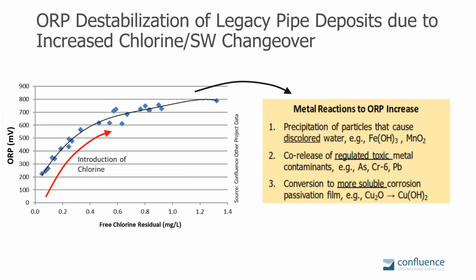An example of the other direction, of increasing chlorine. We're going from unchlorinated wells to chlorinated wells, or areas that historically have consistently had low chlorine, and all of a sudden you make a change, add booster disinfection to try to solve that, and you rapidly increase the chlorine. The types of problems we see, as I've mentioned, are precipitation of particles, such as iron and manganese, that causes co-release of those regulated metals, change in the biofilm, and a quirk with copper, which behaves differently than lead. When you're in low chlorine it forms less soluble copper species, and as you add chlorine, you create more soluble copper species. So during that reequilibration phase, you may see an increase in copper release.